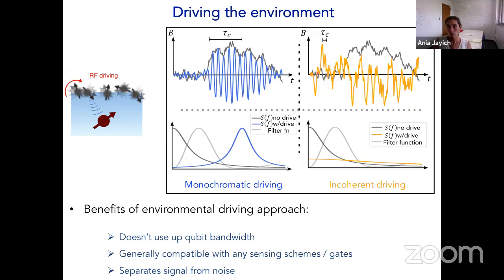So if the gray thing is the magnetic field as a function of time, before applying a drive, it maybe had a correlation time of tau c. But now if I apply an incoherent drive, I'm reducing the correlation time of my environment. When I do that, I effectively flatten the power spectrum, as opposed to shifting it in this case. I flatten the power spectrum. And again, the overlap of my filter function and my power spectrum is now reduced in a different way.